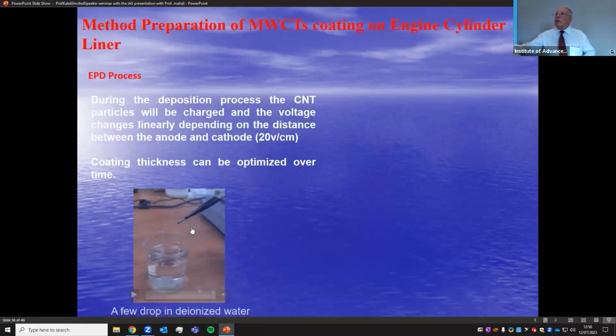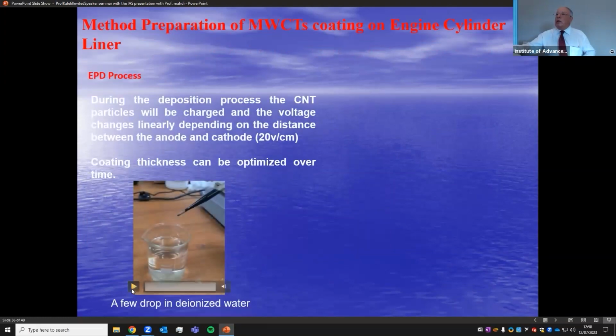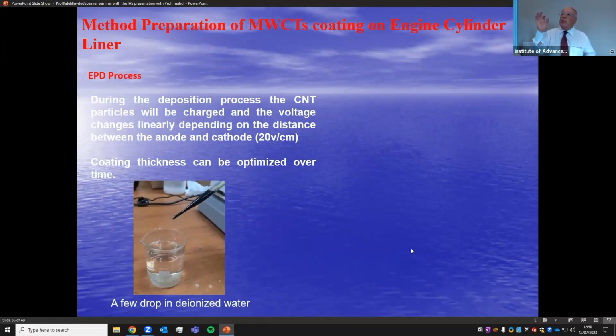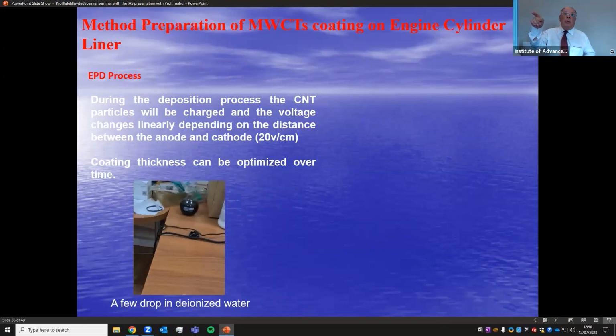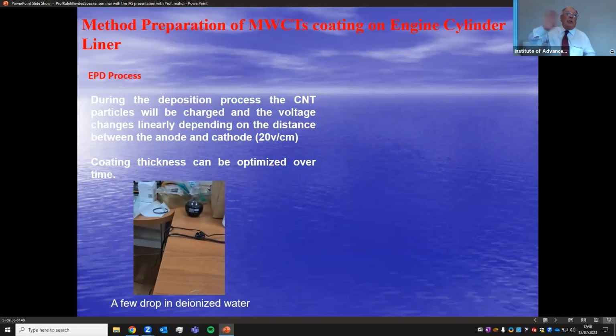Then you must use a few drops of this solution in the deionized water. But we did one drop here. If you increase the drops, it doesn't work. So after many experiments, we have succeeded in this.